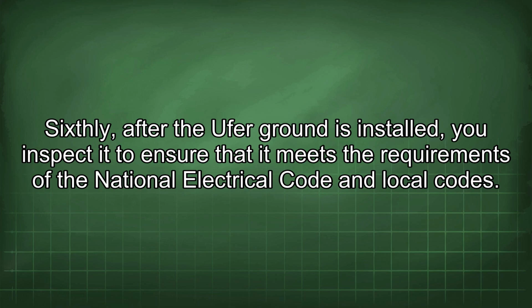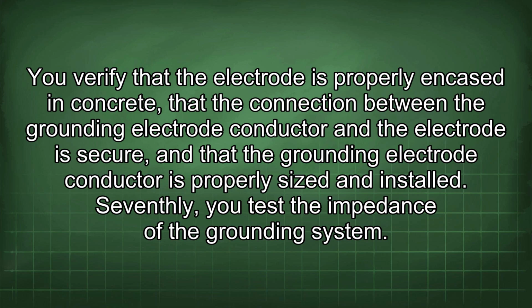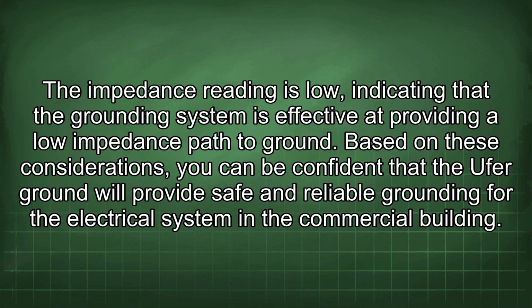Sixthly, after the Ufer ground is installed, you inspect it to ensure that it meets the requirements of the National Electrical Code and local codes. You verify that the electrode is properly encased in concrete, that the connection between the grounding electrode conductor and the electrode is secure, and that the grounding electrode conductor is properly sized and installed. Seventhly, you test the impedance of the grounding system. The impedance reading is low, indicating that the grounding system is effective at providing a low impedance path to ground. Based on these considerations, you can be confident that the Ufer ground will provide safe and reliable grounding for the electrical system in the commercial building.